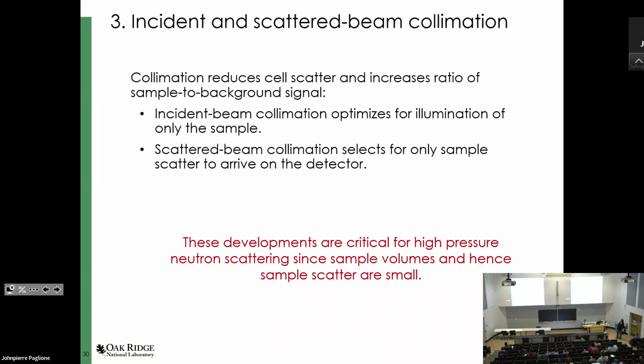So yes, just to summarize this again, we focus a lot on incident beam collimation to make sure we only illuminate the sample. We also work on radial collimation or scattered beam collimation to further improve these things. And of course, these are all critical for high pressure neutron scattering, since our samples are small, sample environments are big. So the signal from your sample can be easily lost in the background.